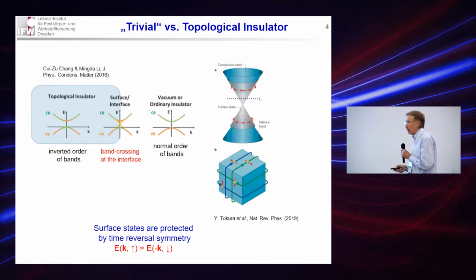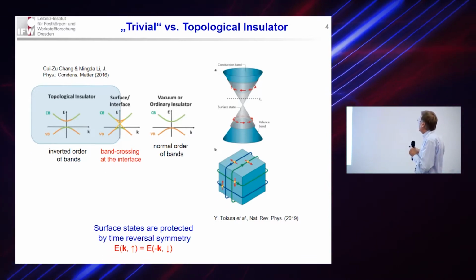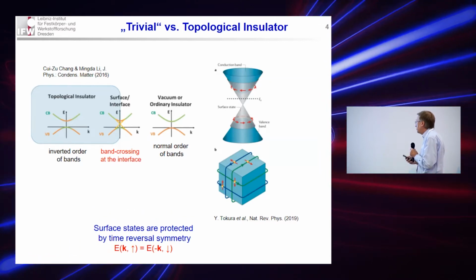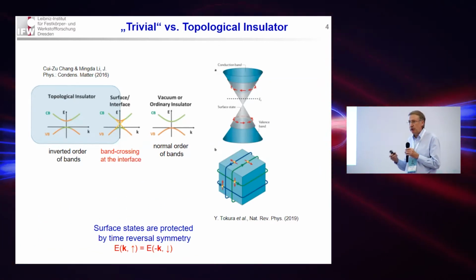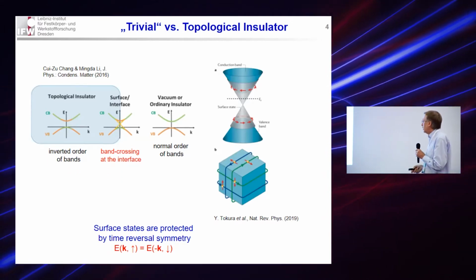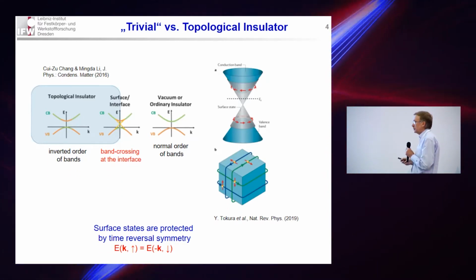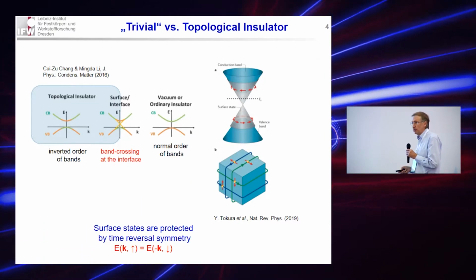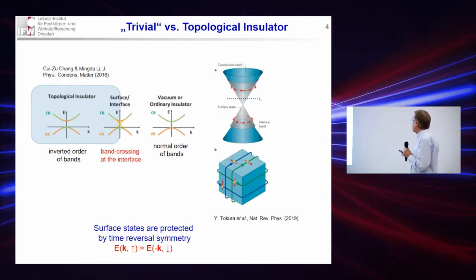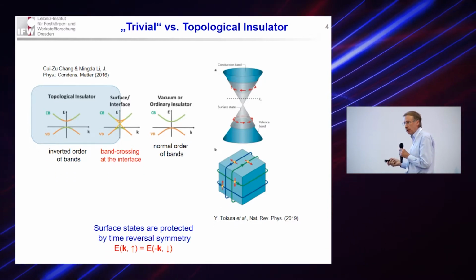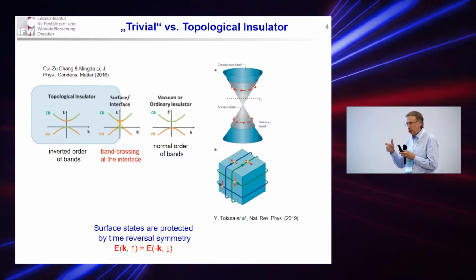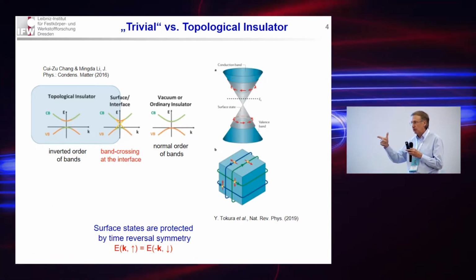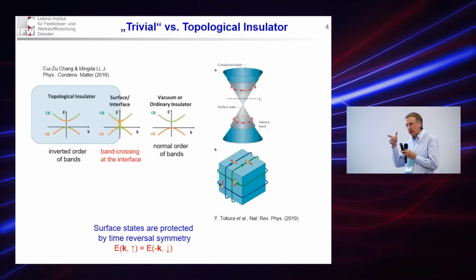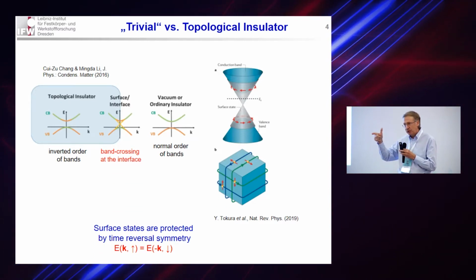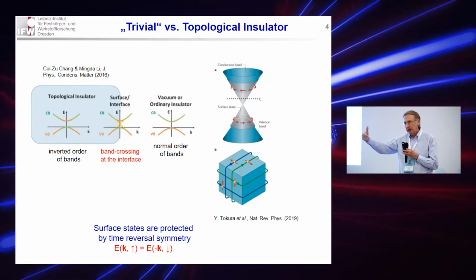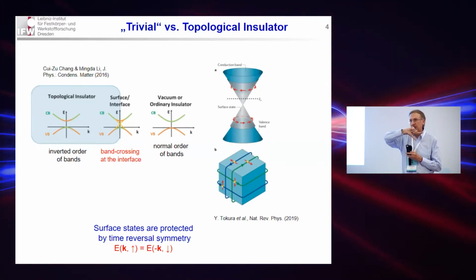So the energy of this electron depends linearly on the momentum. The specific feature of these surface states, which is very important for the physics, is that these states are spin polarized, because they are protected by time inversion symmetry. That means that an electron which has a positive momentum has a certain direction of spin, and because of the spin-orbit coupling, this spin is locked to the momentum. That means if an electron travels in a certain direction, it has spin up, and it can travel in the opposite direction only when it has spin down.